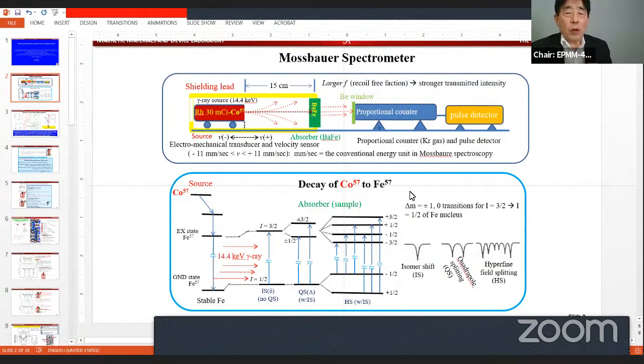And what kind of spectrum are we expecting from this gamma ray radiation on magnetic materials? We have three different spectra. One is a single spectrum, called isomer shift. A double spectrum is called quadrupole splitting. And the last, the hyperfine field, means the six-line spectrum. The observed sample will have combined single, double, and six-line hyperfine field spectra, and then we have to analyze them individually. Therefore, we can obtain magnetic properties from this sample.